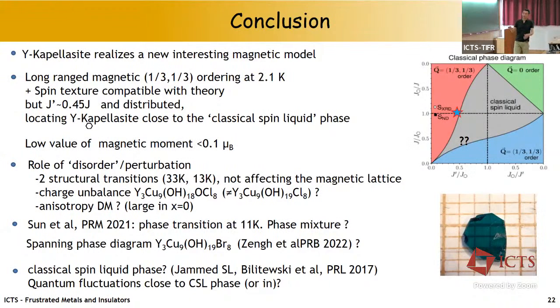What I did not address, because we didn't study it so far, is the role of disorder. What I showed you is that there are some structural issues, but they seem to be small and probably don't affect the magnetic model. Now, I didn't explain, but the formula I showed you is actually charge unbalanced. There is a proton that is missing somehow, so there has to be a bit of substitution on some site, like the chlorine site. I mean, some dilution of this site to maintain the charge, and this is not resolved. So that could be a source of disorder and explain maybe the distribution of the J that we observe.